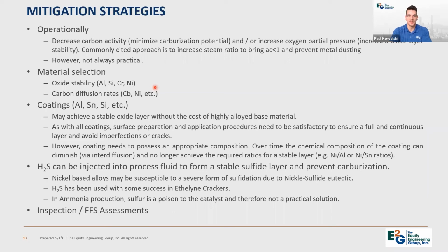And again, the hope is that the coating stays intact, and then the base material is not exposed to the metal dusting atmosphere or damage mechanism. But of course, as with all coatings, surface preparation and application procedures need to be well documented and well maintained to ensure a good quality coating and ensure that it stays intact and there are no imperfections or cracking in the coating. If there are any imperfections, then obviously the base material is exposed and the coating is not doing the job of protecting the material from metal dusting.